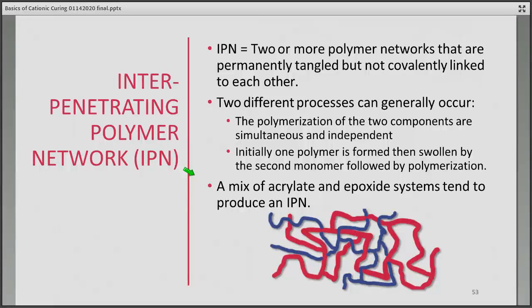Two different processes can generally occur when you're forming that tanglement. You can get a polymerization of the two components simultaneously, so you have both reacting independently, and as they're growing your polymer chain, they just grow around each other, and you get your tangled ball of polymer. Or you can initially have one polymer being formed, so it reacts first, so you get your polymer. It's then swollen by the liquid monomer of your other component, and then that polymerizes. So you can think of it as both happening at the same time, or first one and then the other.